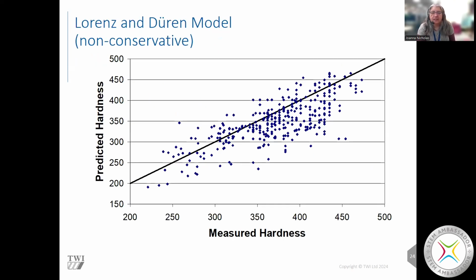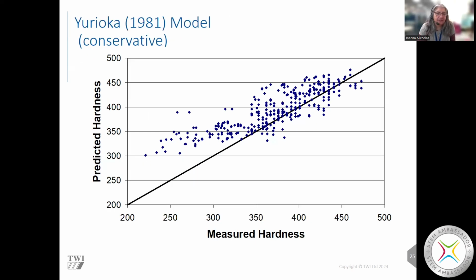Here's my data using one of the models that was in the published literature, our predicted hardness from the model against the measured hardness. Most of those dots show that the measured hardness was higher than what was predicted. Most of the dots are underneath the line, which suggests that the model is generally unconservative. This one from 1981, also the line was just the wrong side. It wasn't everything in the middle. It was biased towards the left, which then meant that the model was over-predicting the hardness. So these empirical models that had been generated by these researchers some time ago didn't quite work.